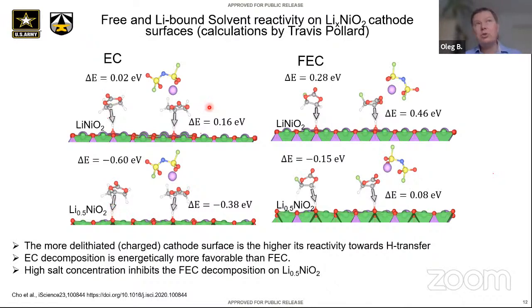And another trend is there was a lot of focus on trying to stabilize electrolytes by having high concentrations. That has two sides. One is higher concentration, as I'll show at the end, even for sulfides, it limits their solubility. So it limits solubility of products which were generated during decomposition, right? So then you form CEI much faster, but also it does have an offset and stabilizes the electrolyte against H transfer. So when Travis took EC and put lithium FSI next to it, binding to EC, the H transfer became less favorable by about 0.2 eV. Right, so if you go to very high concentration, that might buy you another 0.2 eV, and that's consistent with the, say, once we have a delithiation of the surface, and energy becomes not 0.6 but 0.38, again close to 0.2 eV.